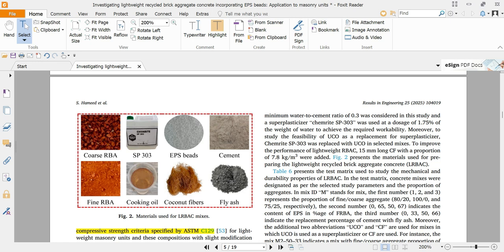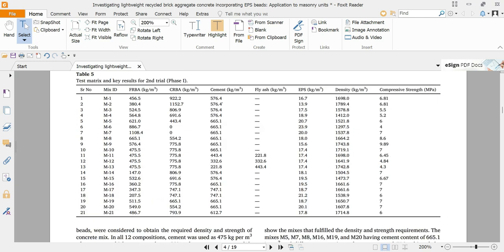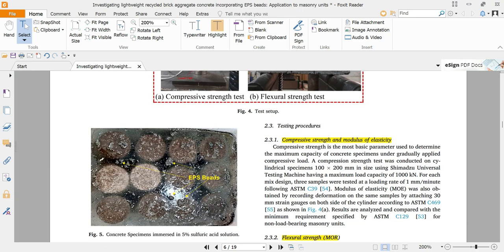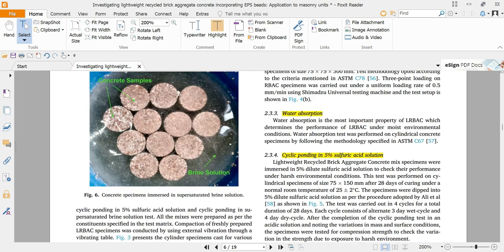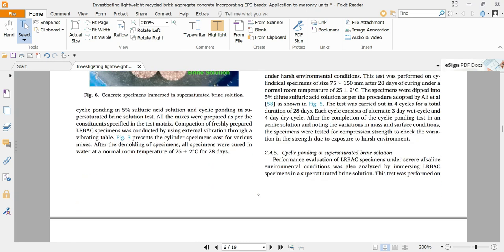And our aim was to produce a concrete which is lightweight, and as per ASTM C129, the density of lightweight concrete should be between 1400 kilogram per cubic meter to 1680 kilogram per cubic meter. Here we made some trials to produce the concrete with the required density. We played with the quantity of EPS beads so that we can get our required density as well as our required strength. Then we performed some mechanical properties tests as well as some durability tests like cyclic bonding in 5% sulfuric acid solution and cyclic bonding in supersaturated brine solution.